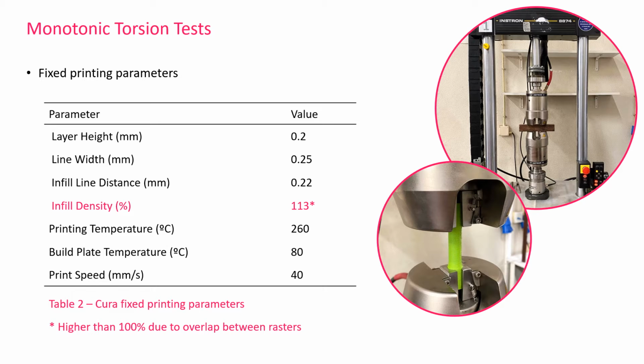Because an overlap between adjacent printed rasters was introduced, an infill percentage of 113 was used rather than 100. Infill was printed before walls, followed by the inner wall and so on until the last external wall was printed.